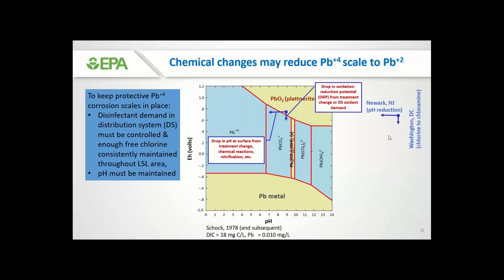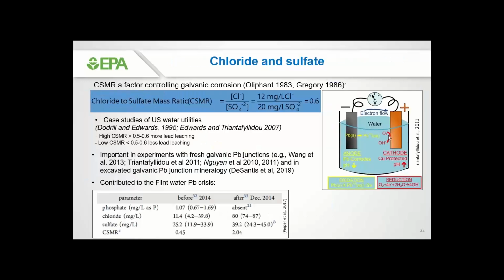So in order to make sure that we don't have lead leaching problems, we need to ensure that we have high free chlorine residual throughout our system and low chlorine demand in our system, so that we can maintain that ORP high enough throughout areas of our distribution system where we have lead service lines. And of course, the pH must be maintained as well.